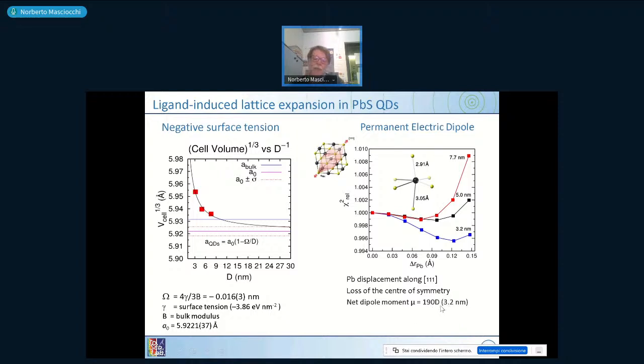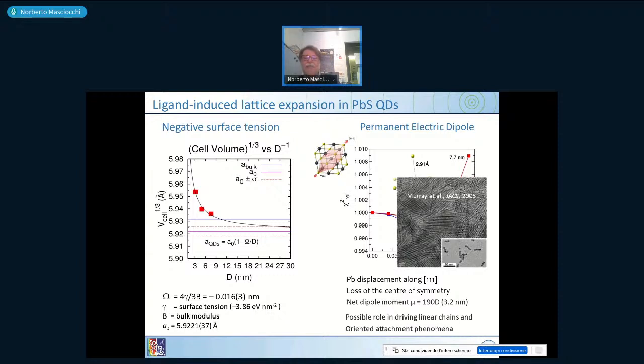Is that dipole moment important? It is rather relevant because Murray in 2005 found that these tiny nanoparticles, if deposited on a surface, align in tiny sequences of beads, of spheres. So the spheres are not equally distributed on the surface, but try to align as if they were each one a tiny magnet or tiny dipole. And this was not understood. You can see also from the figure down here that by depositing very separate PbS particles, so not so dense, still you have a preference for having chains of spheres and not randomly distributed spheres. This was called the oriented attachment phenomenon. It was eventually discovered and interpreted by this dipole moment.